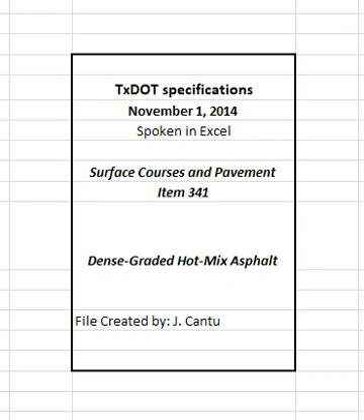The engineer will take immediate possession of the untrimmed cores and submit the untrimmed cores to the construction division, where they will be trimmed if necessary and tested for bulk specific gravity within 10 working days of receipt. The average bulk specific gravity of the cores will be divided by the engineer's average maximum theoretical specific gravity for that lot to determine the new payment adjustment factor of the sublot in question.